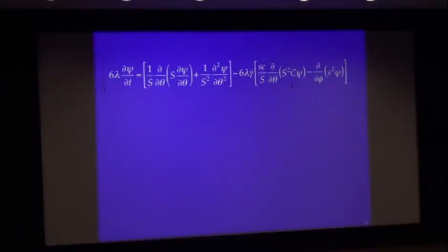Now let's look at that continuity equation that I talk about for orientation. You see, here is the time evolution derivative on the left. This thing is called an orientation distribution function, and what we're headed towards are movies of that thing. And it depends on both of the spherical coordinates. So at rest, this is a sphere, right? The orientation distribution is the same in all directions, so we'll normalize that to a constant 1 over 4 pi. And then when the liquid deforms, some interesting stuff will happen. You can't really look into this very easily experimentally. So I think this is an example where theory lets me look deeply into the liquid and get some ideas about how the molecules are creating those higher harmonics.